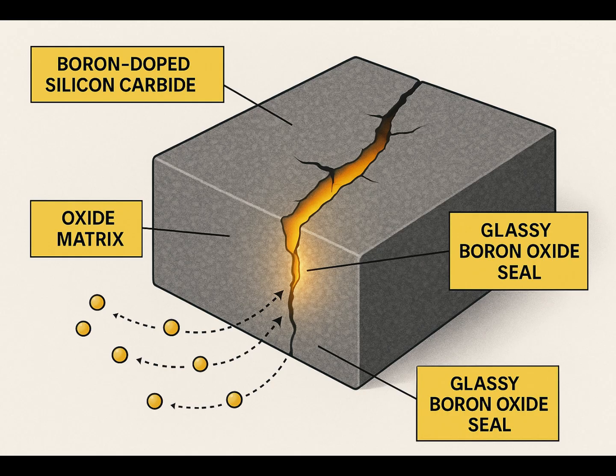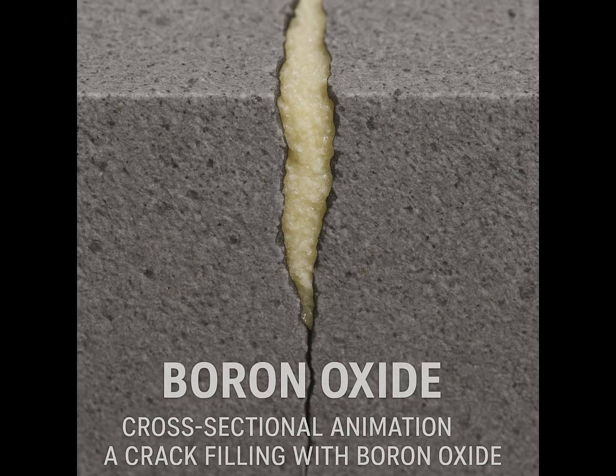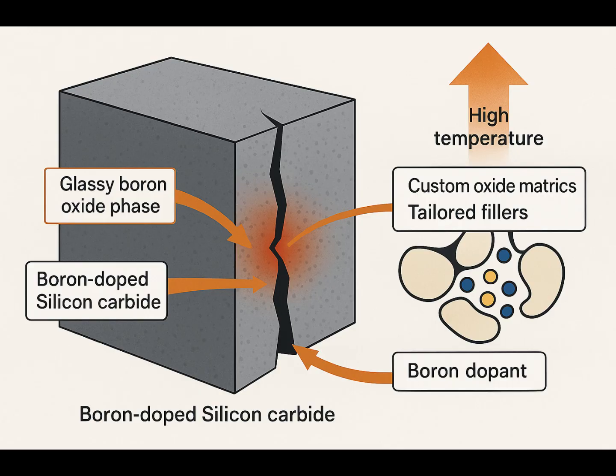Self-healing ceramics for hypersonic background. High-temperature simulation of thermal protection system cracking. We're developing self-healing ceramic materials engineered to autonomously repair cracks at operating temperatures above 1,500 degrees Celsius. The core concept is this: we embed boron-doped silicon carbide into an oxide matrix. At elevated temperatures, if a crack forms, boron migrates to the damaged region and reacts to form a glassy boron oxide seal. That seal fills the crack, restores structural continuity, and halts further damage propagation.